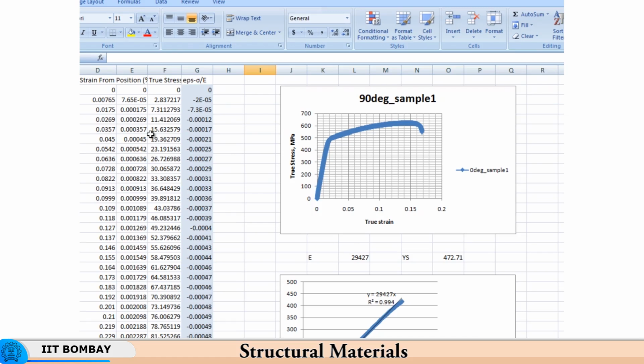So, that is the reason why you need to give 0.2% plastic strain, so that you can be sure. For all practical purposes you can be sure that the entire sample, all the grains in the sample, have reached the yield point. So, that is the reason why we have 0.2% offset or 0.2% proof stress.